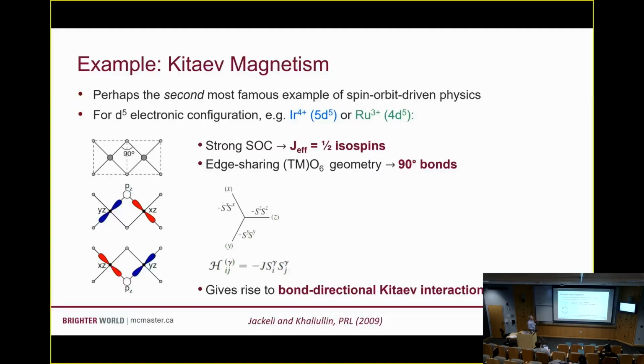If you have materials that are based on edge-sharing octahedral crystal structures, so if you have this kind of bond geometry here, where we've got a transition metal and then oxygens connecting it, then the magnetic interactions, the superexchange, run through these transition metal-oxygen-transition metal pathways, and the superexchange through the upper and lower pathways here cancel out through these bonds. Your normal Heisenberg interactions disappear, and you get these really unusual bond-directional interactions that we call Kitaev interactions.